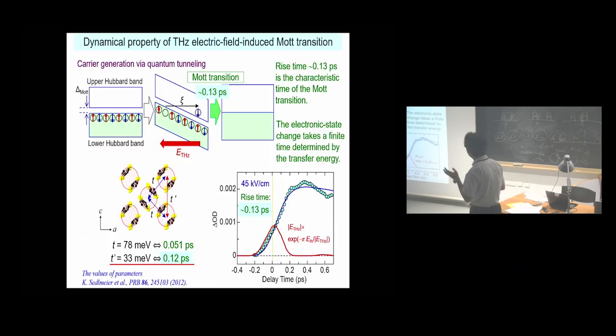Okay, so this rise time is 0.13 picosecond. This is the electronic response, and after that, the molecular displacement occurs coherently. But that period is about 1 picosecond. So the initial process is purely electronic.